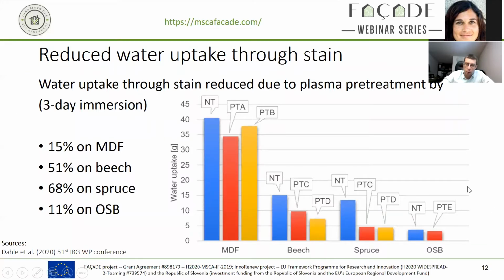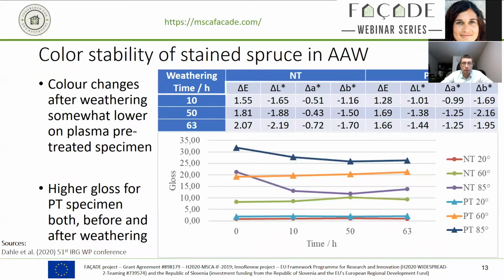On samples like OSB, with those larger defects and generally less well spreading and covering of the stains, we found a minor impact, but we found a really major reduction of the water uptake on spruce, still a significant one on beech, and also a notable one on the MDF material. So resistivity to moisture and water is definitely something that can be improved, and that will then also increase the lifetime of any object that I produce out of this, or where this is going to be used in the production.